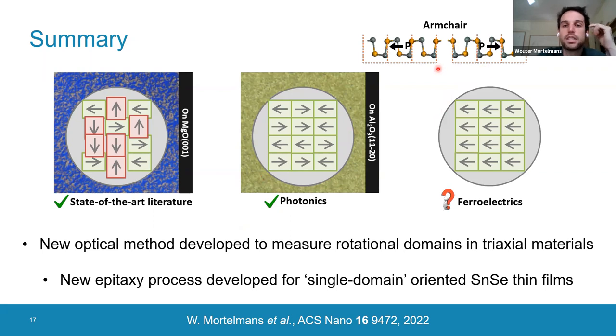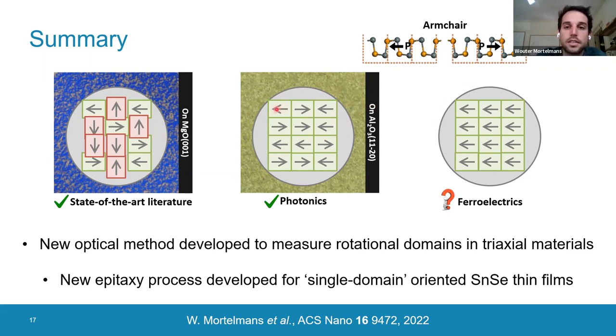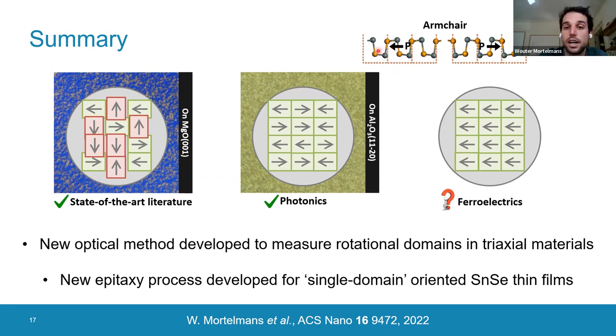One more aspect: we know from the crystal structure that every individual layer has a polar moment — an electrical dipole in every layer. This optical technique is not sensitive to this electrical dipole, so it's still possible these dipoles point in different orientations. We're currently investigating second harmonic generation or piezo-response force microscopy to measure this polar moment. If we can switch this polarization, it could be interesting for in-plane ferroelectric applications.